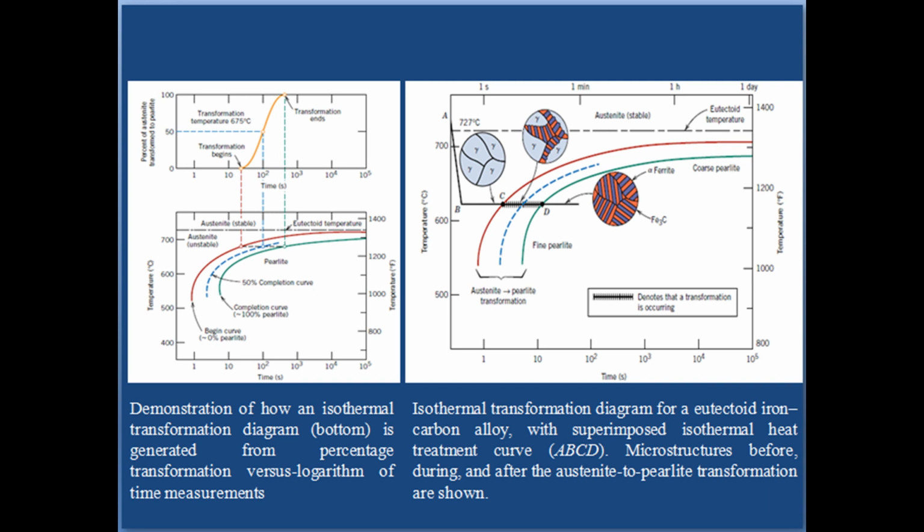At these temperatures, diffusion rates are relatively high, such that during the transformation illustrated in the figure, carbon atoms can diffuse relatively long distances, which results in the formation of thick lamellae. With decreasing temperature, the carbon diffusion rate decreases and the layers become progressively thinner. The thin-layered structure produced in the vicinity of 540° is termed fine pearlite. This is also indicated in the figure.